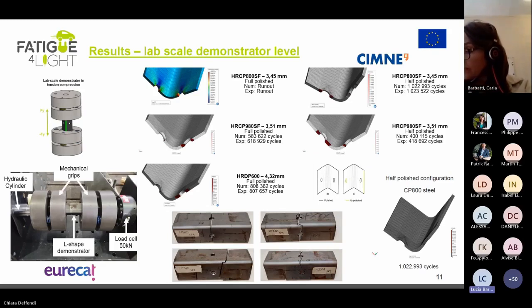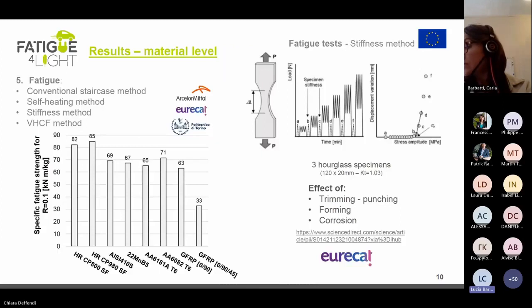And this is a very interesting approach because here, for instance, with only 3 hourglass specimens and in about 4 hours, you can already get a very good approximation, actually, of the fatigue limit of a specific material. And how is this test performed?